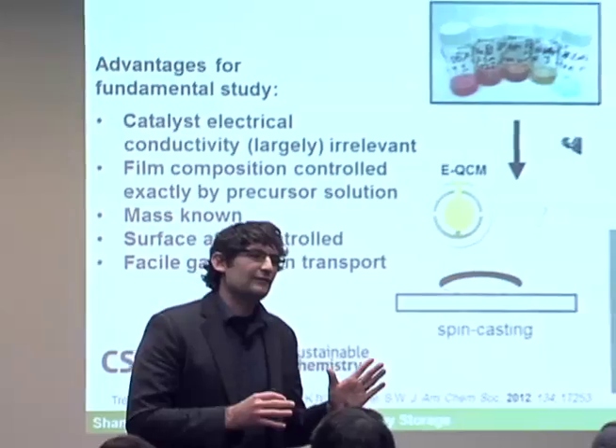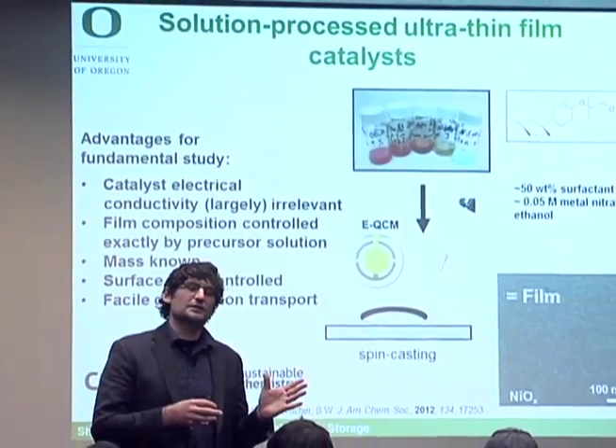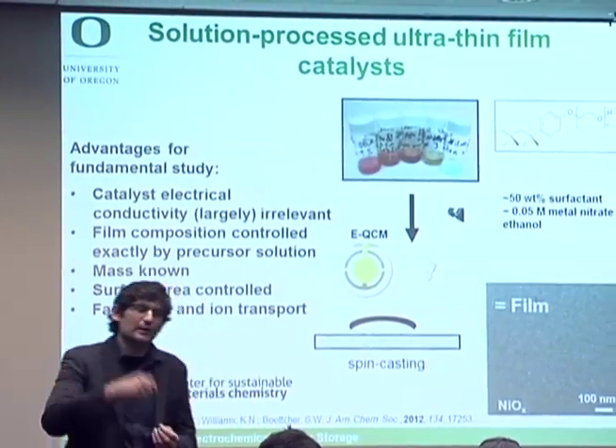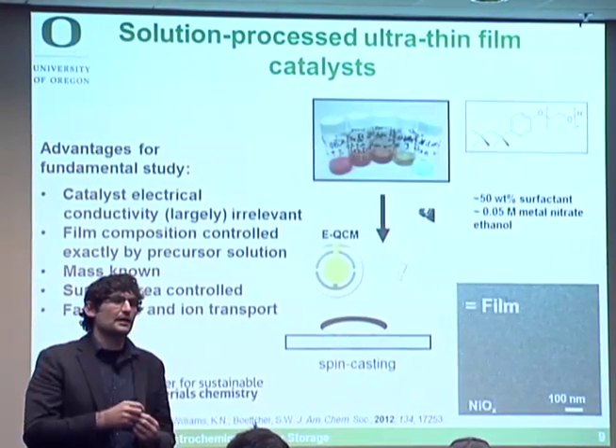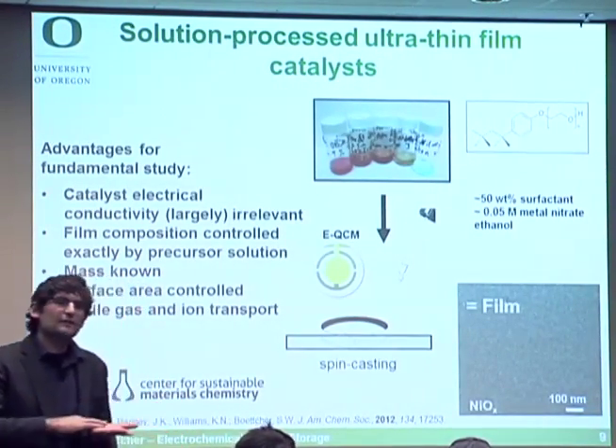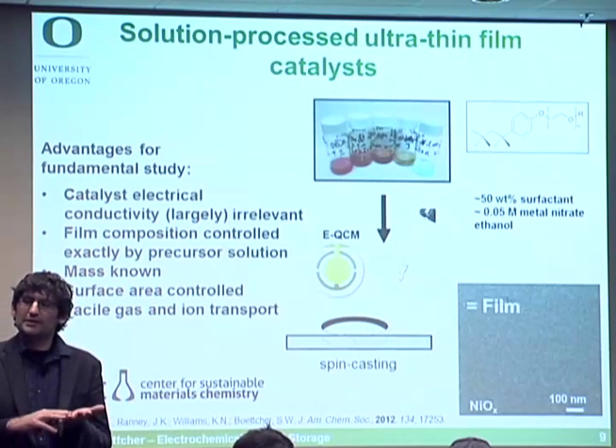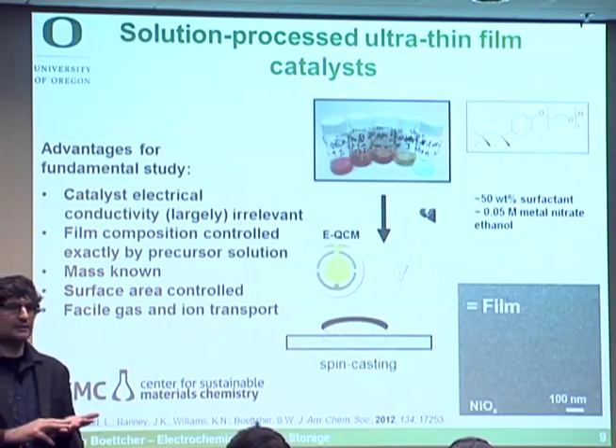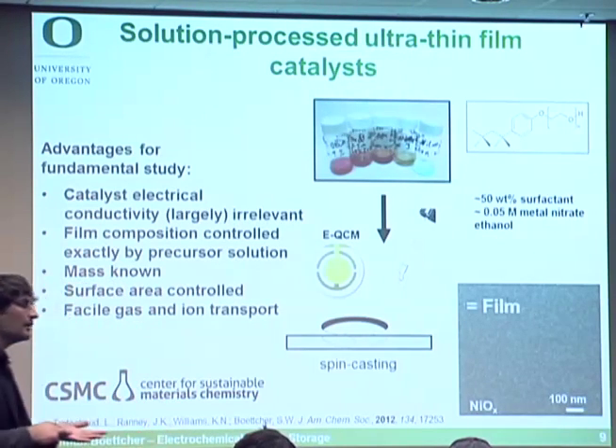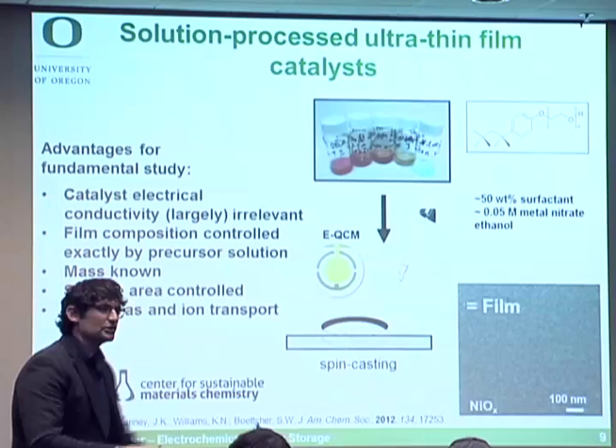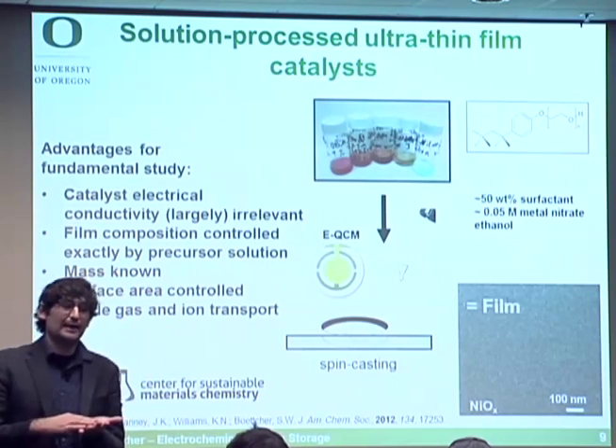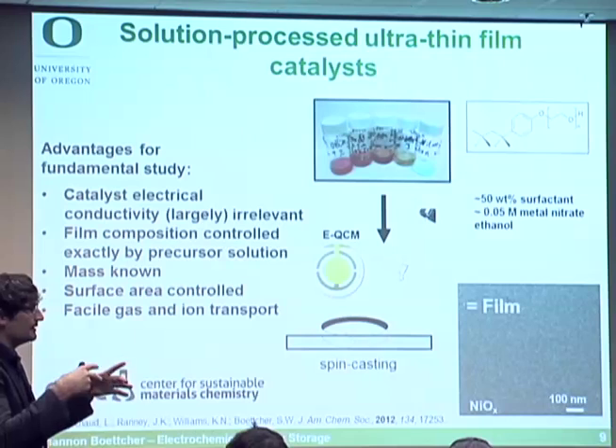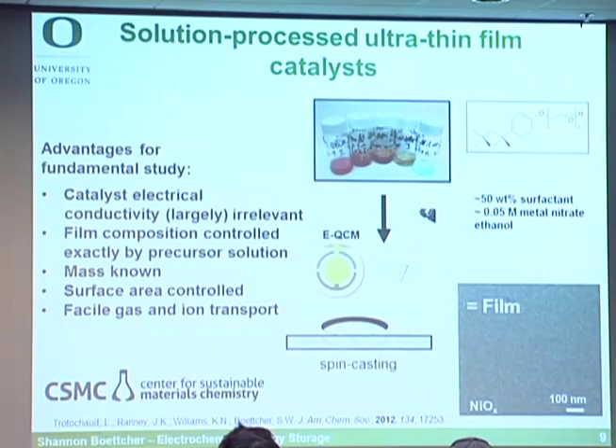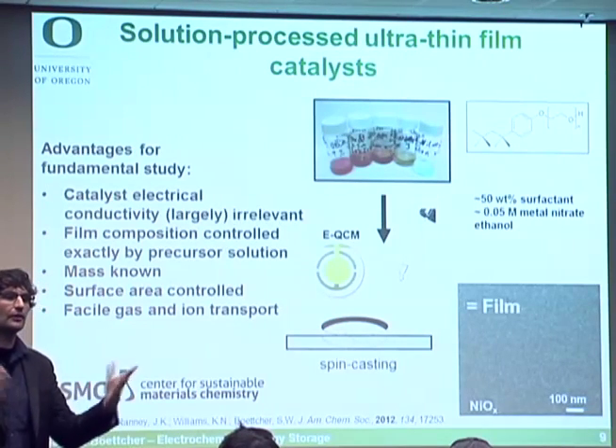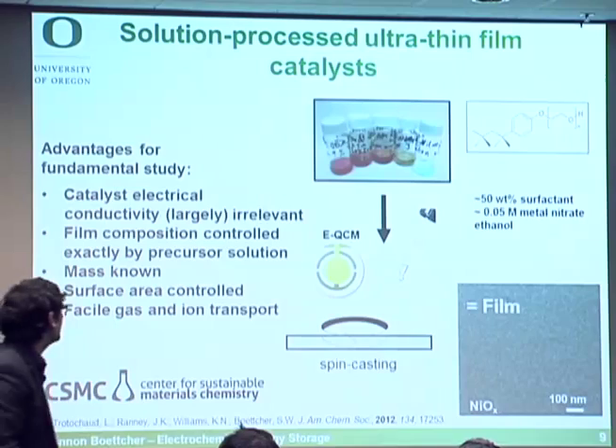We said, well, if we want to understand oxygen electrocatalysis, and we think there are these factors of electron transport through high surface area materials, of mass transport, let's just make very thin films of the various monometallic transition metal oxides. We'll do experiments on an electrochemical quartz crystal microbalance, so we can just weigh the amount of material we put down. It's an oscillator, and the resonance frequency tells you the mass of the material there, and you can measure it to sub-monolayer precision, so you can see if it's dissolving or if something else is plating. You can see if it's changing with time.